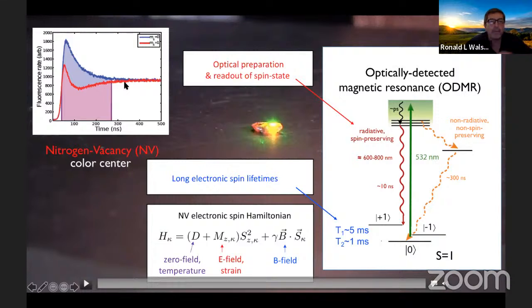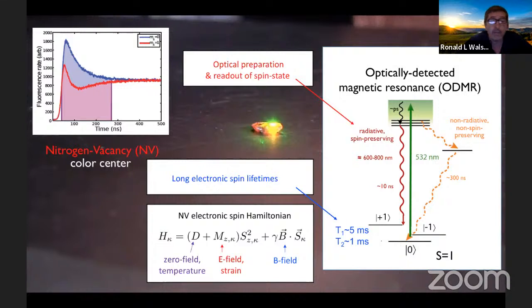So this has two key properties. One property is that in the long run, just wait a microsecond or half a microsecond, regardless of what spin state you began in or any mixture of spin states, when the NV is illuminated with green light, it ultimately gets pumped into and placed into ms equals 0. That's optical spin state preparation. The very first thing that happens in almost every NV experiment is you illuminate the NV or the NVs with a little green light for a microsecond or so, and that prepares them all into the ms equals 0 state. That's the beginning. That allows you to do anything beyond that.